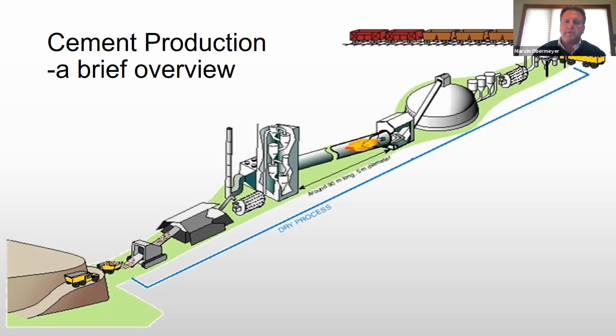These particles are very hot. At this point, they're 2,600 degrees Fahrenheit. So they go into a clinker cooler, which is cooled by an enormous amount of air. The air is blown through the material, and years ago, I'm assuming that this air was wasted, but they capture the air now and put it back from the clinker cooler into the preheater tower. It usually comes in the middle, and this simple illustration doesn't show that, but it usually comes right about here. So basically every BTU of heat is wrenched out of that flame, okay? All of it is reused and fully used, and that makes our plants more efficient, which is huge in this conversation.